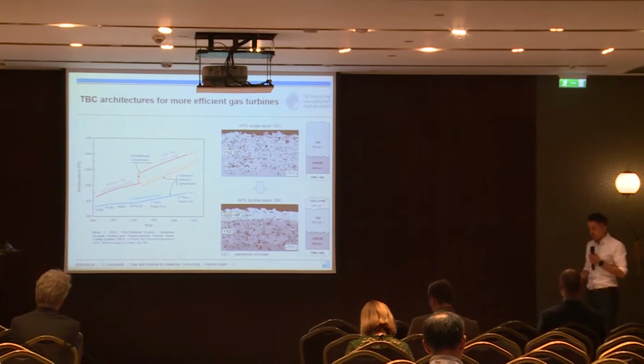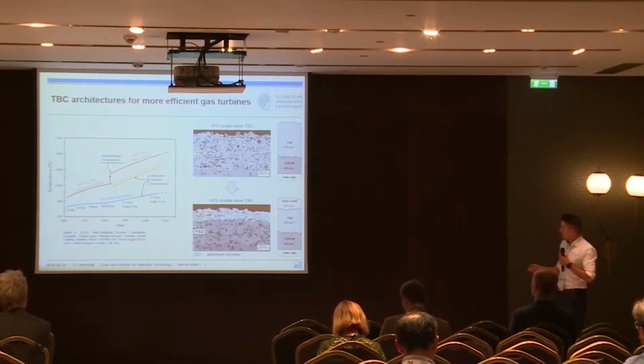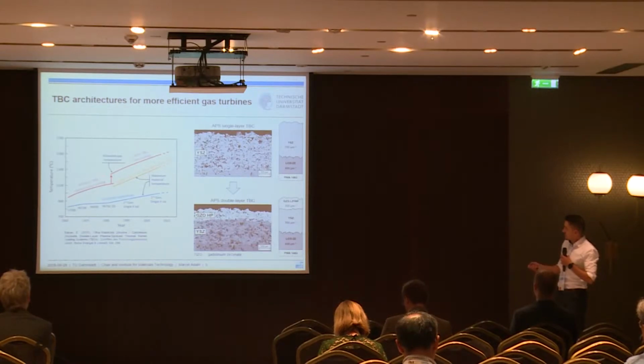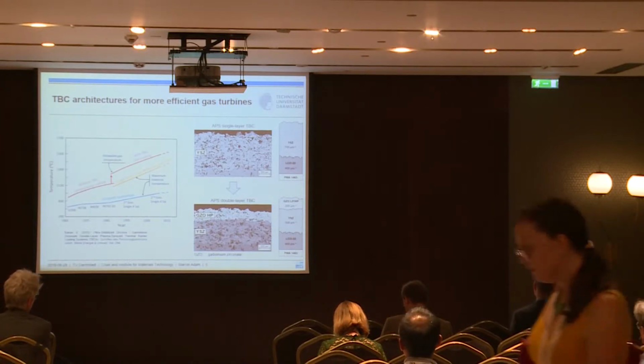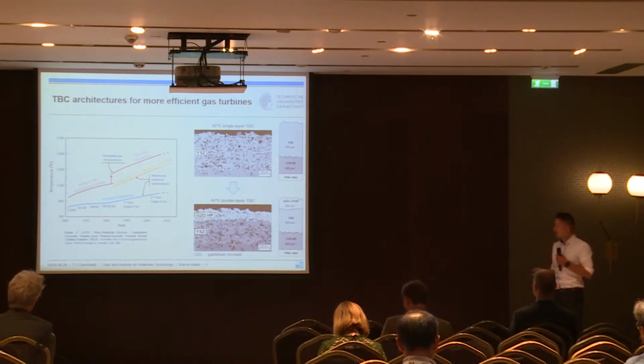Having a look at the history of high-temperature materials, we clearly see that single-layer thermal barrier coatings have been used for nearly 30 years. Since that time, we have been limited to maximum material temperatures of about 1,200 degrees Celsius. But the gas turbine industry requests more efficient gas turbines, which means we have to produce thermal barrier coatings that can resist temperatures of maybe up to 1,500 degrees, for example.